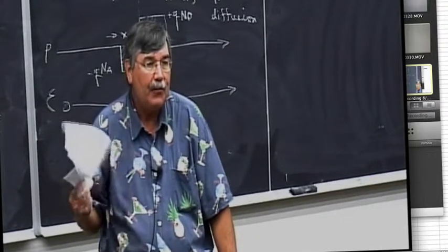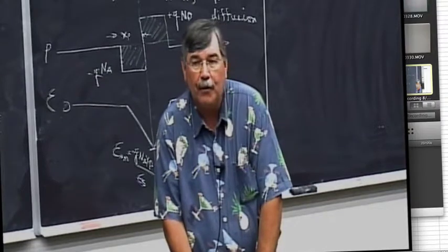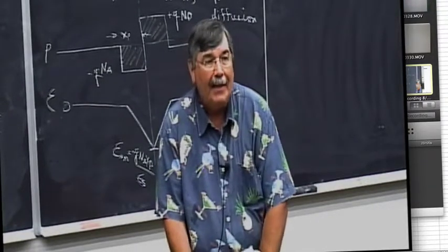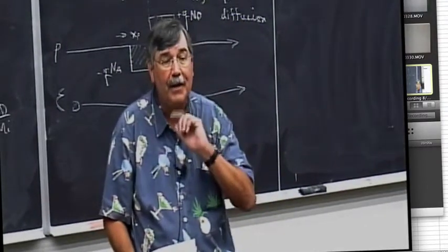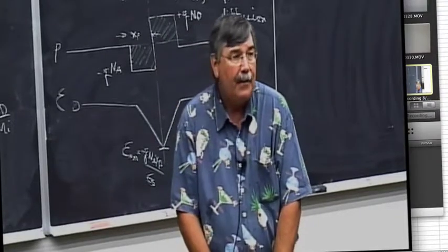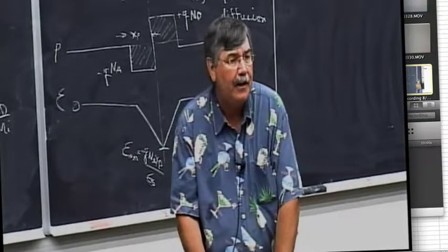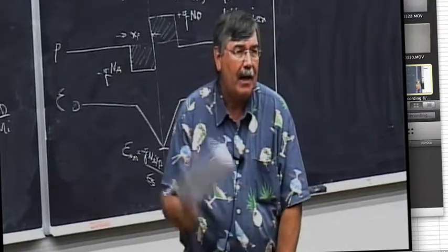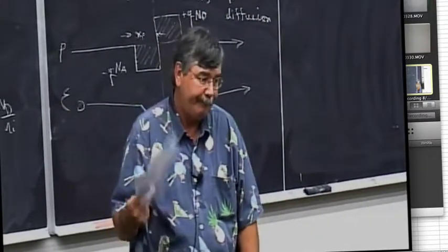And the second thing is, generally when we have a p-n junction, the way we build it, it's really important that one side is almost always much more heavily doped than the other. And that's very nice because it simplifies the equations a lot. Now I'm getting ready to do some derivations, and I'm going to assume that Na is much greater than Nd. It turns out that in every practical application we will do for the next 2 semesters, that's a perfectly good assumption.